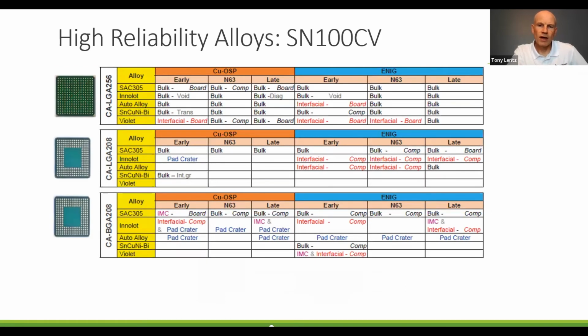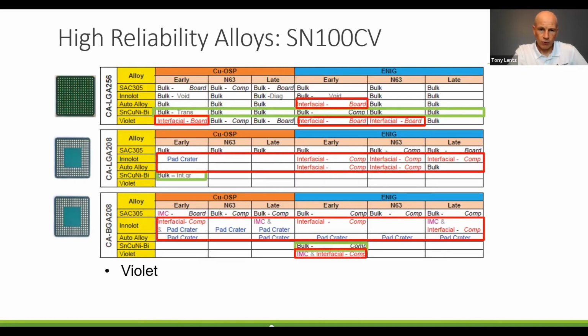Here's a summary of failure modes for those alloys that were studied in that work. I'm just going to cruise through this pretty quickly. So Violet was tested, which is a proprietary alloy that's being evaluated for reliability purposes. It tended to fail at the interfacial and IMC layers. So it failed between the component and the solder joint and between the board pad and the solder joint.